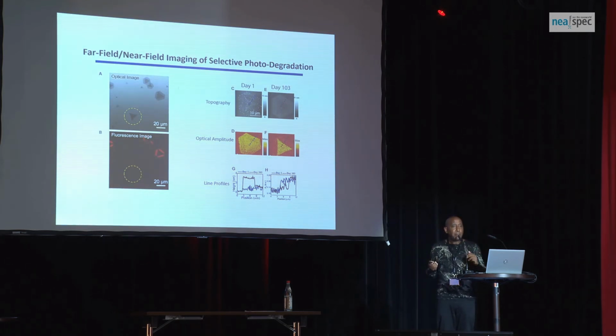This is also known. But the other thing is the dielectric function, which, as Rainer talked about, the real part of the dielectric function is directly related to the amplitude, as you all know. And so what you see is an amplitude image of the flake before experiment and after the outer layer has completely degraded here. So if you compare in the beginning, both of them have the same amplitude contrast, which means very similar dielectric constant at 632 nanometer. And this is true. These are measured for monolayers of these materials. So you see the same contrast, so near field correctly picks that.